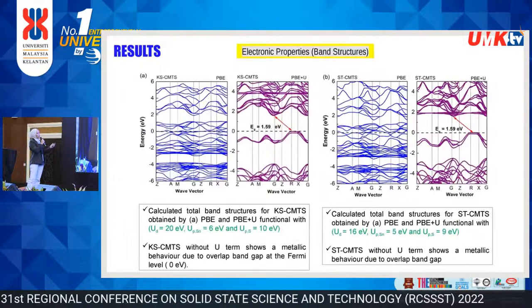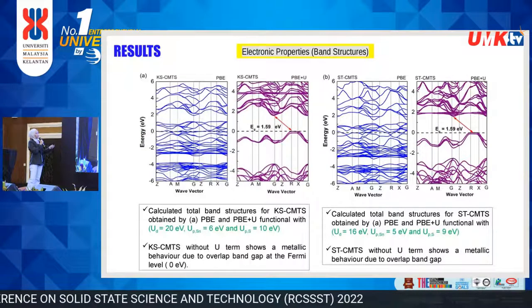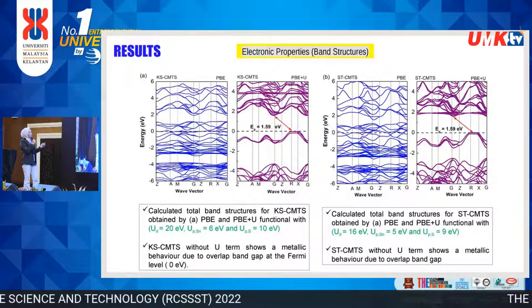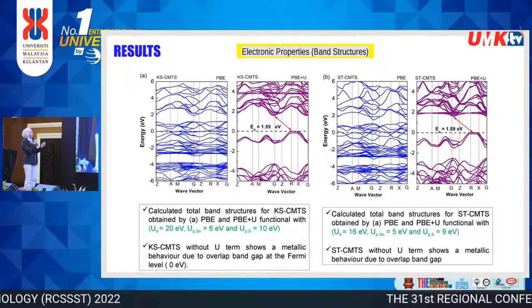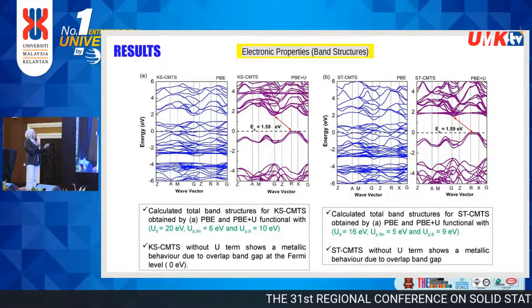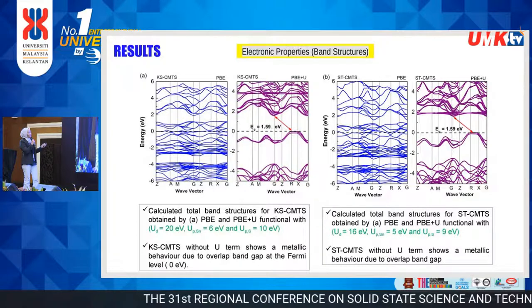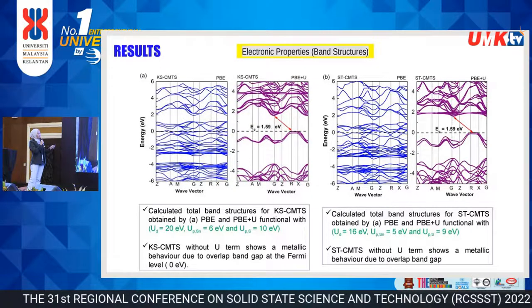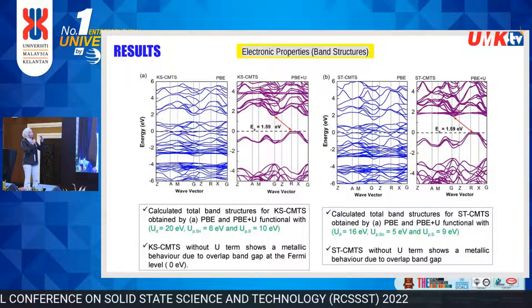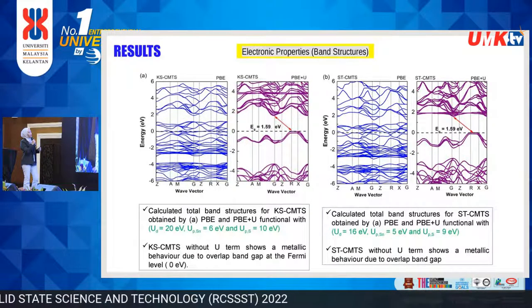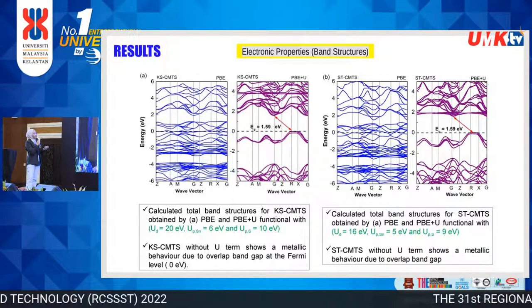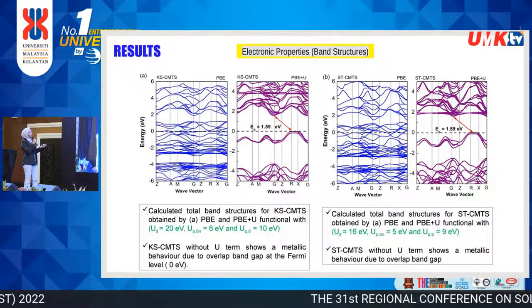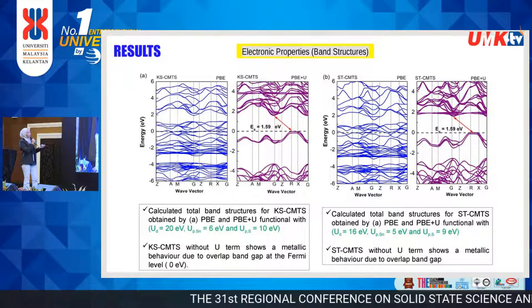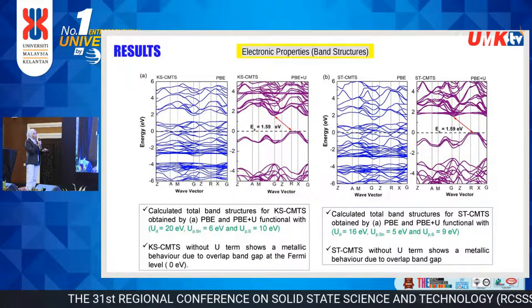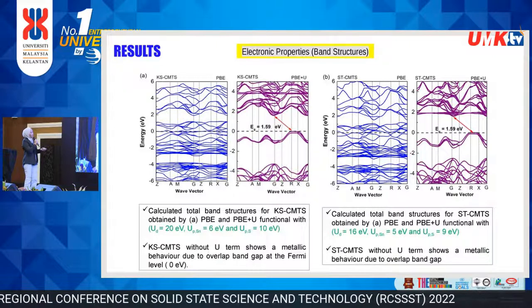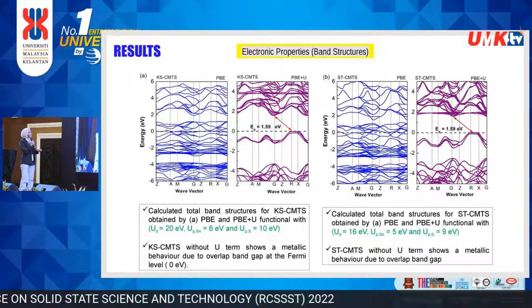Okay, this is the band structure. The blue band here is the standard DFT without Hubbard U. There is no band gap; the bands overlap at the Fermi level, 0 eV. And after the Hubbard U is implemented, the band gap appears at the lower conduction band from the Fermi level, from 0 electron volt, and we can get the band gap of 1.59 electron volt. So this can be validated with the experimental value.